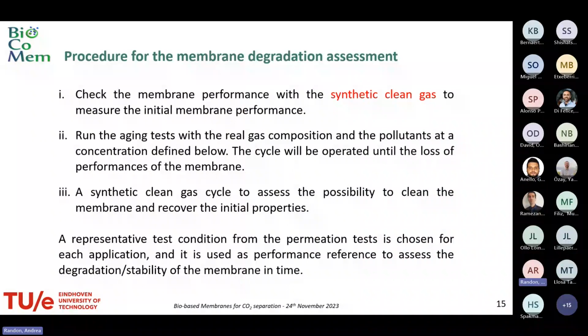What we do is basically send in first place the synthetic clean gas, assess the performance of the membrane, the separation of the membrane. Then we run aging testing cycles of 24 hours each of the real gas composition, which is chemically attacking the membrane. And then after 24 hours, we send again the synthetic clean gas and we see if the performance we are finding now is worse than the one before, basically with the first one. And if it's not too worse, we just repeat the cycle until we reach what we want.